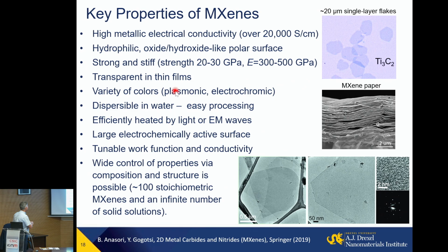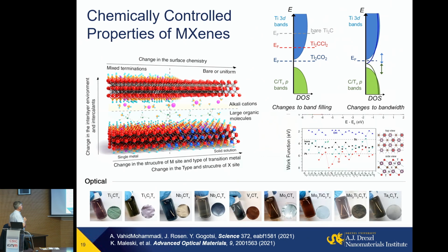What it means is a variety of electronic and optical, optoelectronic properties, plasmonic, electrochromic. And they're among the most efficient, almost 100% light to heat absorbers within their absorption band. Plus they have a large electrochemical active surface. But the key thing is that all these properties are highly tunable. In other aspects, they look like other two-dimensional materials. Single crystals you see from high resolution TEM and selected area diffraction. They can be assembled into MXene paper, very similar to graphene paper. And those bulk properties measured on paper, when you have hundreds, thousands of junctions between the flakes, still show very high conductivity, and again, dispersible in water as you have seen.